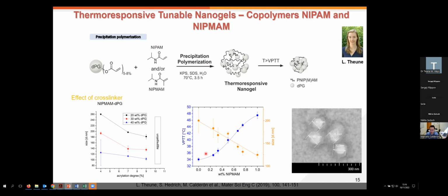So here we can see that with 100% NIPAM, we have a transition temperature of around 34, 35 degrees. And then when we start copolymerizing with NIPMAM, this increases. And in the case of 100% NIPMAM copolymerized with a cross-linker, we have a transition temperature around 46 degrees. So we have here a range of materials that will eventually enable us to test at least two ways of triggering with temperature that we have, either the natural gradient of the skin or irradiation with an infrared lamp.